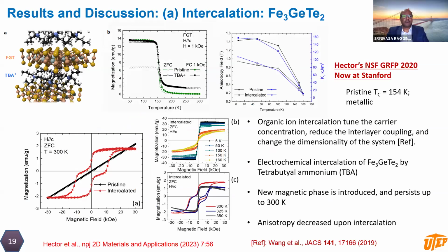The first project is on how one can tune the magnetic properties of these materials by intercalating this material using an organic molecule. For example, we started with the tetrabutylammonium cation here, and we intercalated that between the two iron germanium telluride layers. Okay, so we did a bunch of magnetic measurements, before we intercalated the compound with the TBA plus, and after.